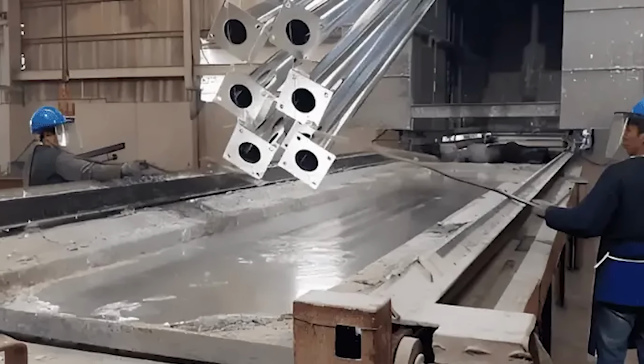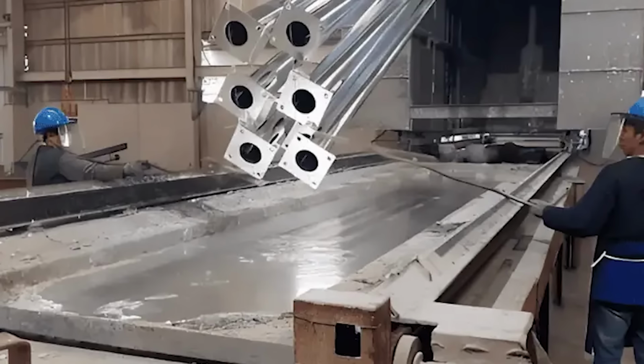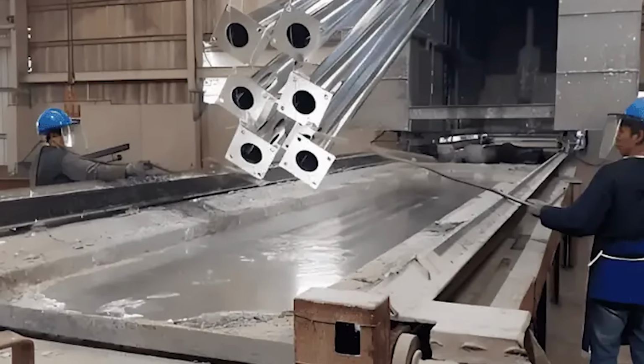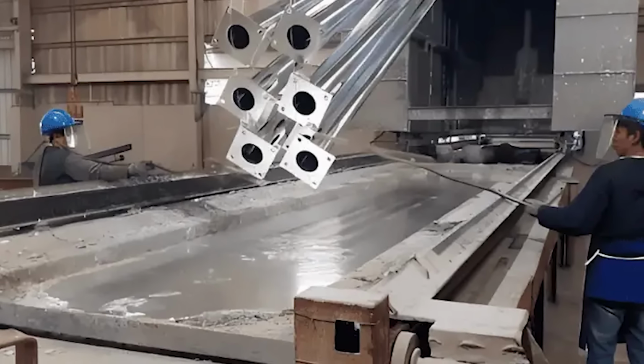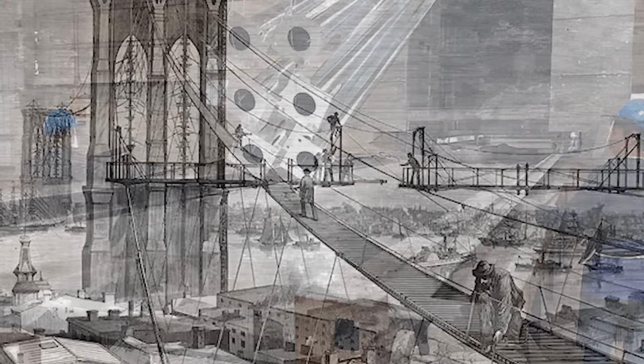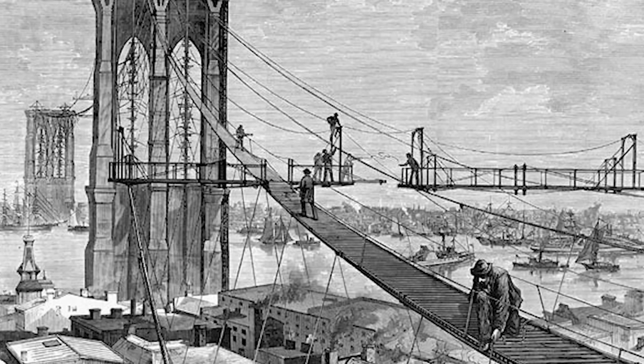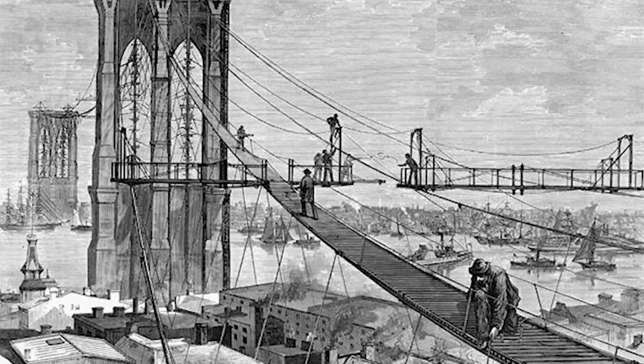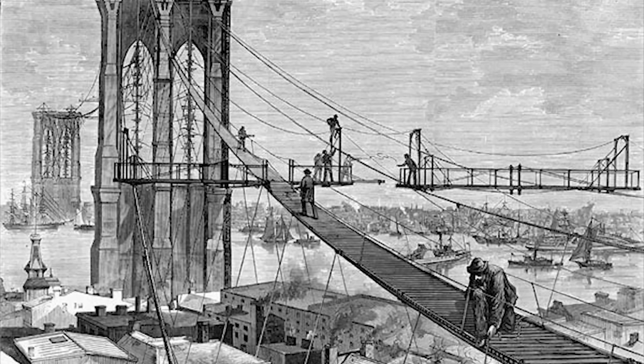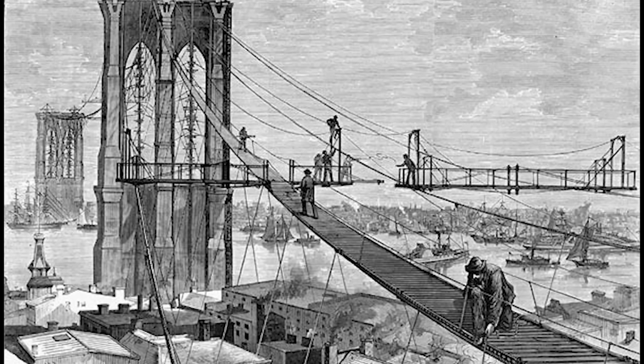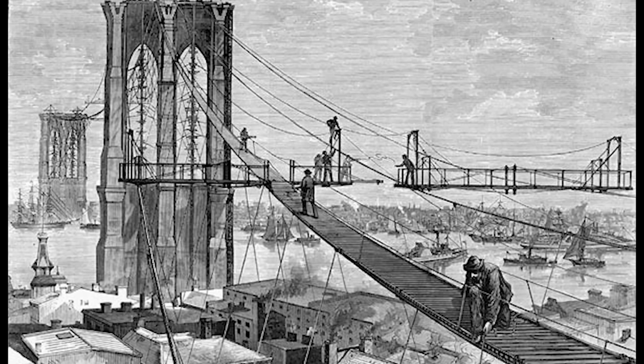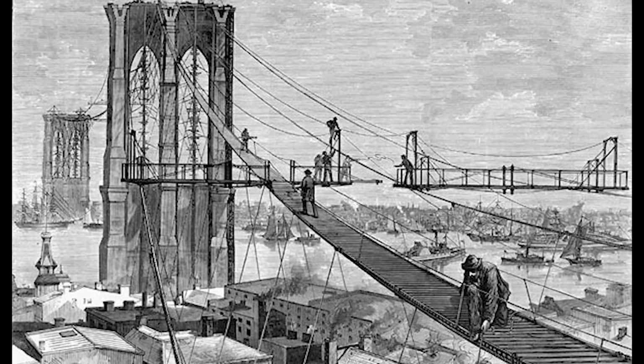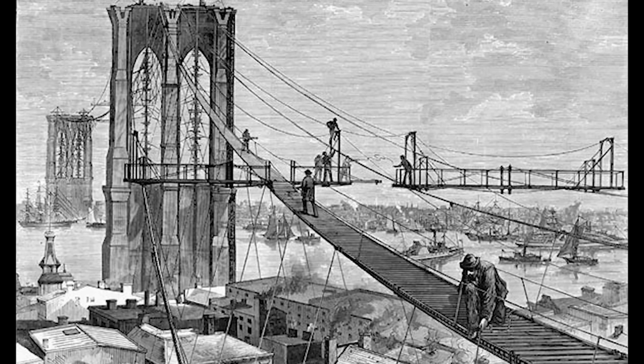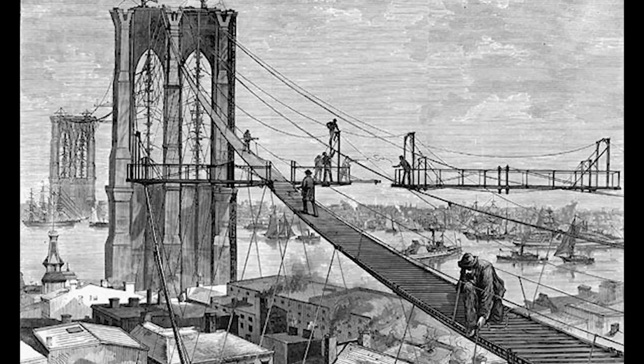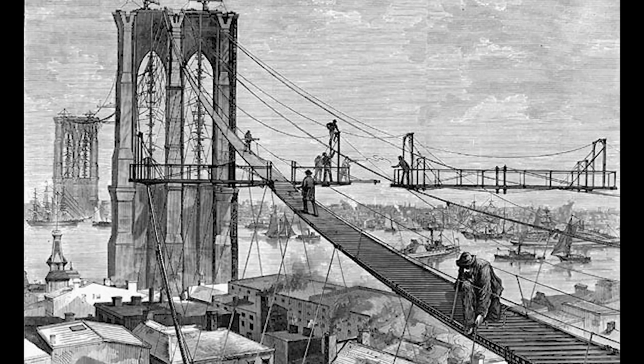The cable system began resembling a sealed pressure vessel designed to exclude air and moisture from the structural steel within. The galvanized main wires provided sacrificial protection at the steel surface. The galvanized wrapping wire eliminated gaps where water could penetrate. The red lead paste filled microscopic voids. The multiple paint coats shed atmospheric moisture and resisted chemical attack from industrial pollutants.